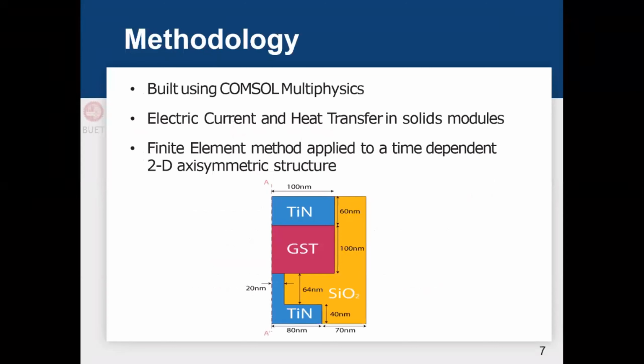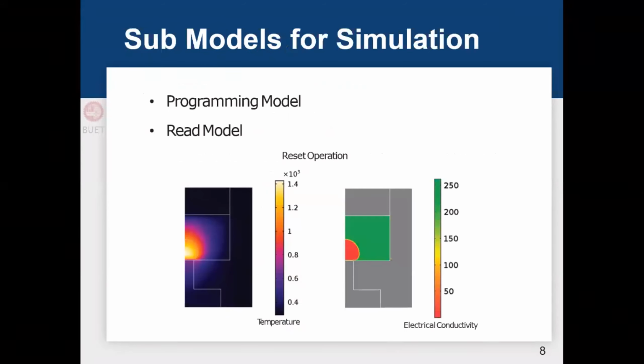This is the device that we actually modeled in COMSOL Multiphysics in the 2D axisymmetric structure, where the GST is surrounded by a top electrode and a bottom electrode of titanium nitride, and the whole device is surrounded by silicon dioxide. We've chosen to investigate two submodels for our simulation. One is programming and another one is read model.